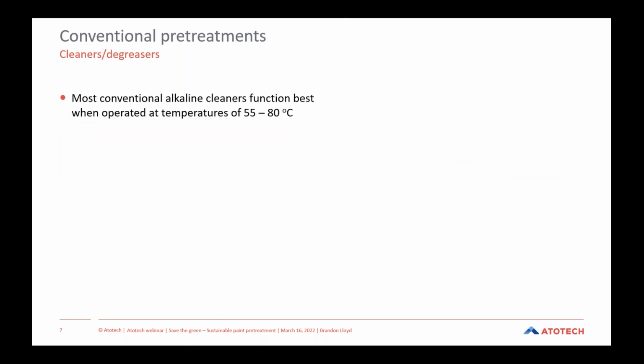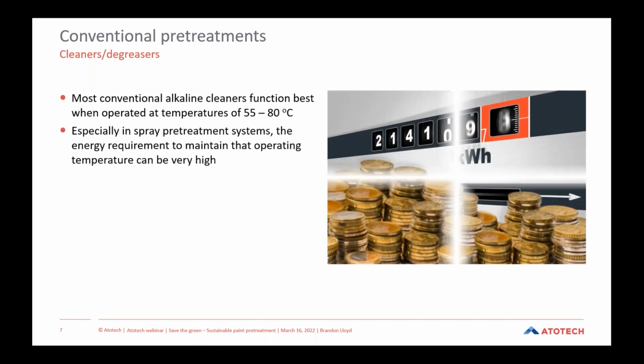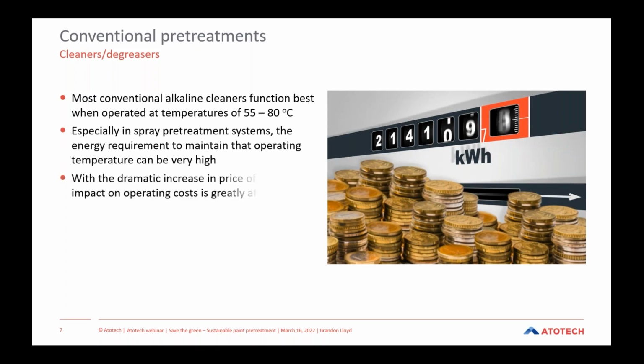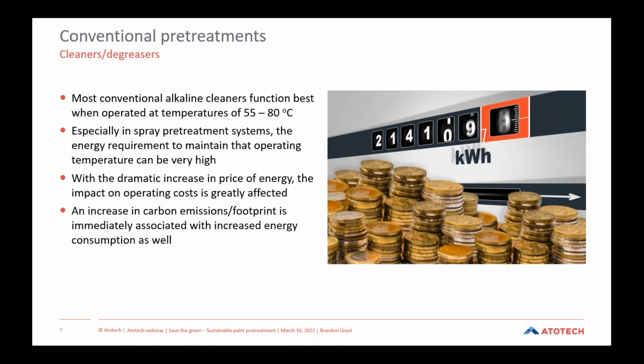Most conventional alkaline cleaners do function best when they're operated in a temperature range of 55 to 80 degrees Celsius. Especially in spray pretreatment systems, the energy requirement to maintain that operating temperature can be quite high. So with the dramatic increase of price of energy, especially in the last few years, the overall operating costs can be greatly impacted because of this. An increase in the carbon emissions or carbon footprint is immediately associated with this high level of energy consumption as well.